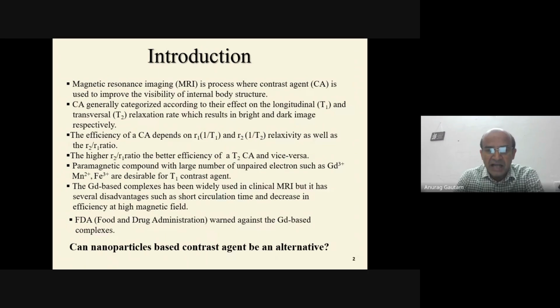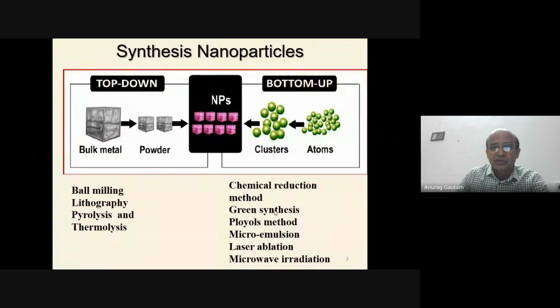For that purpose, iron oxide or iron is not very suitable, because of the differences in the size of the cation. So rare earth based nanoparticles can be better in that respect. That's why we are trying them, because iron oxide quenches the luminescence heavily, but these rare earth based tetrafluorides produce good optical imaging. So they can be used for that. So can nanoparticles be an alternative contrast agent? Yes, certainly. So these are some methods.